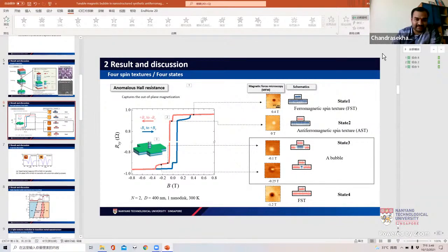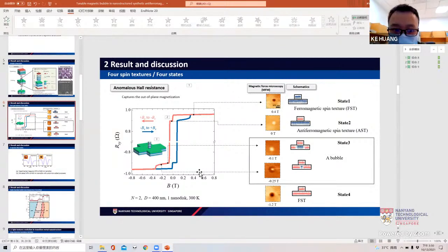Yes, Prem, you can ask. You have time. So my question is about your MFM in magnetic field. You are applying a field as high as 1.2 Tesla. Is your tip magnetization flipping? Yes, of course. I think the coercivity of the tip, if I'm not wrong, is about 200 Oe. So after 200 Oe, which is about 0.02 Tesla, the magnetization of the tip is flipped. Okay.